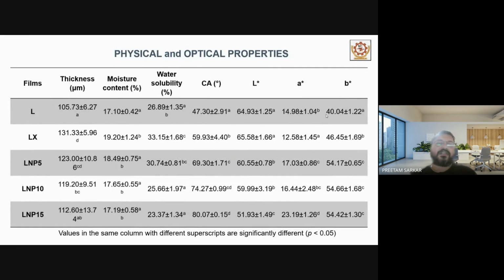Then the physical properties, starting from thickness, which is a very important parameter of food packaging material. We talk about moisture content. As you can see, there is an initial increase and then it is very similar, not much of a difference with the addition of the LNPs. Water solubility is also very important because we want the films to be as resistant to water as possible. We don't want the materials to degrade very fast. Water solubility ranges from 26% to 33%, then 30, 25, and 23%. For contact angle, with the addition of nanoparticles it really improved from 47.3 to 80 degrees, which is very high. We also saw L star, a star, b star, which are the color parameters.